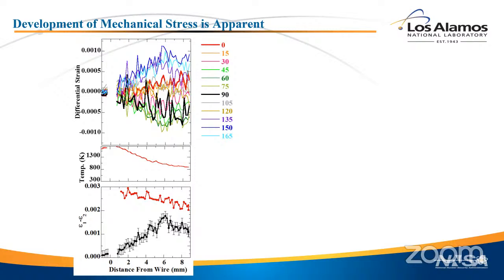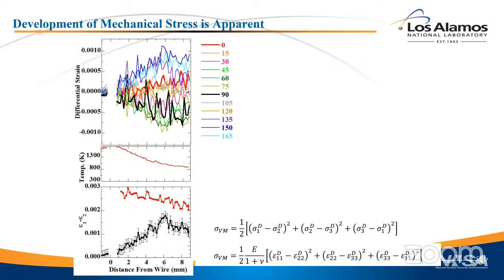But what it comes down to is we only measure in one plane, right? In order to get a full tensor, you have to be able to measure in 3 dimensions, and we can only measure in 2. What I can do, though, is find the von Mises stress, because with all of these subtraction terms a lot of things fall out. I can actually find the von Mises stress with some level of accuracy, even only measuring in 2 dimensions instead of 3, with a set of very reasonable assumptions.